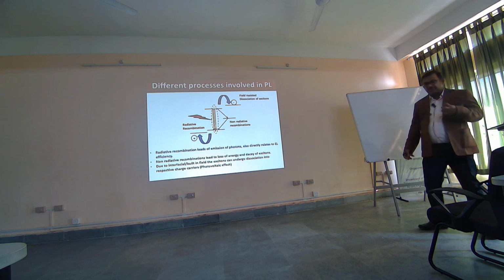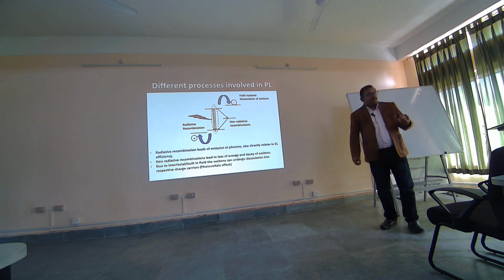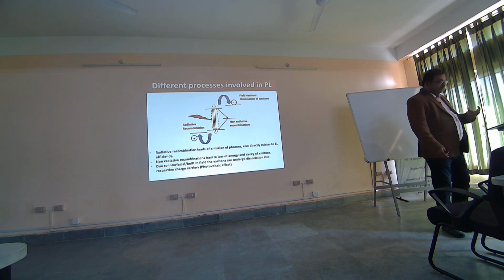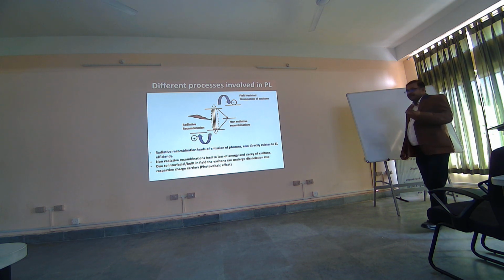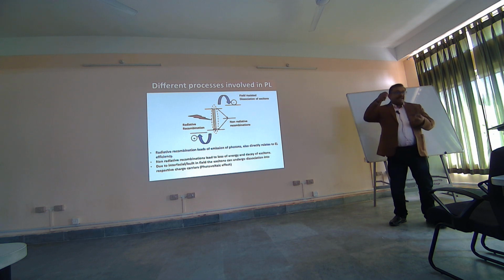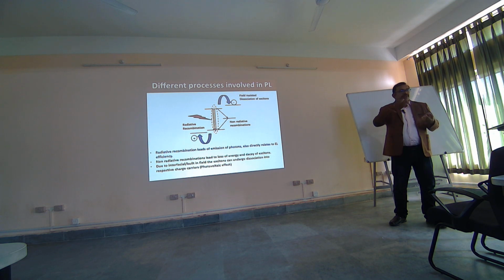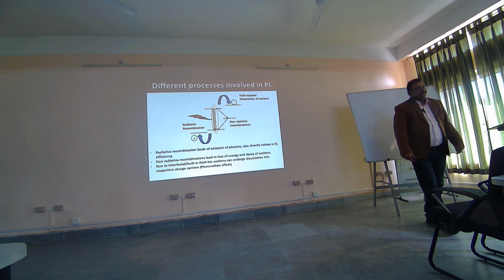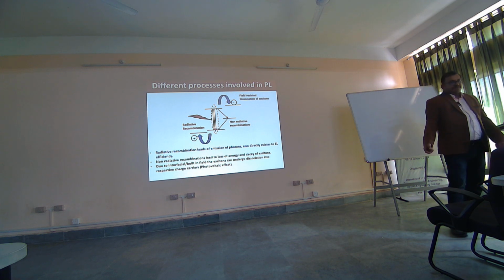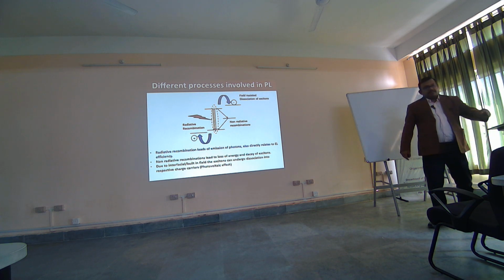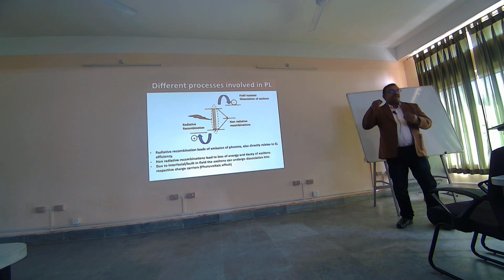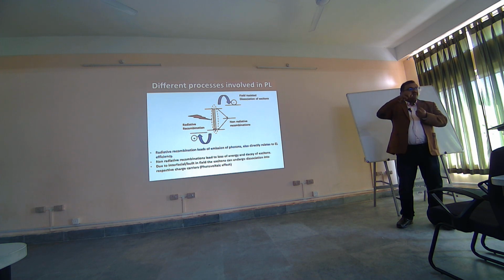For example, if I talk about zinc oxide, zinc oxide at room temperature has an exciton binding energy of 60 millielectron volt. So 60 millielectron volt would mean that the binding energy is larger than the thermal energy for semiconductor devices. What is that? It is 25 millielectron volt. You might have studied, right? So the thermal energy is 25 millielectron volt. So if the binding energy of excitons is 60 millielectron volts, that means the thermal vibrations are not going to cause any disruption to my excitons.